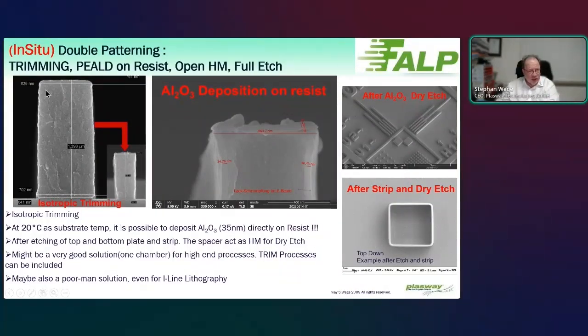So for example, this is a resist structure after lithography. So in the order of 700 nanometer here is a CD, but with isotropic step-by-step ALE etching, we can bring it down to maybe 200 nanometer. And in our reactor, and this is also a specialty, we can work even at 20 degrees C to deposit directly on the resist, with atomic layer deposition, an aluminum oxide film. So we can control very nicely here at the side the future CD.